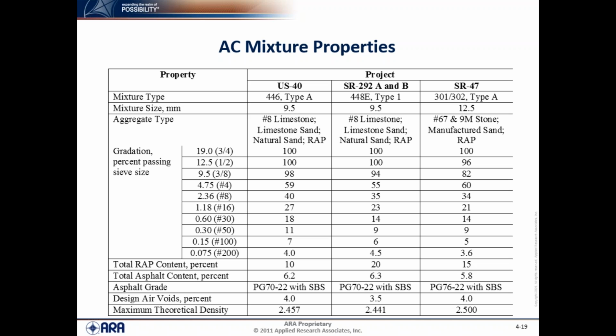Okay. I put this in, this is in the report, but just kind of get an idea of the AC mixture properties in terms of the mix design, to show that there are differences between some of the mixes and there are similarities. Probably the key is for our projects on the US 40 and the 2 projects on State Route 292, those were all a 9.5 nominal maximum size aggregate, or 9.5 millimeter type mixes, designed, I believe, in accordance with SuperPave. I've shown the gradations. The US 40 was a mix 446 type A. The 292 was a 448E type 1.